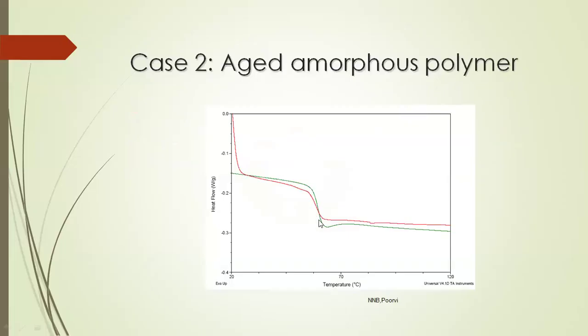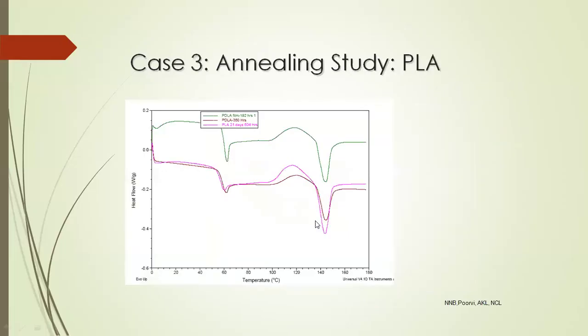in the case of polymers, because polymer crystallinity is going to affect the mechanical properties of the end product. Then this we have already discussed, the polymer. Again, you can study annealing. Particularly PLA annealing studies are very important because you can control the crystallinity of any polymer by annealing the polymer. You can study that using the DSC, and you can manufacture or synthesize the product of desired properties by annealing.